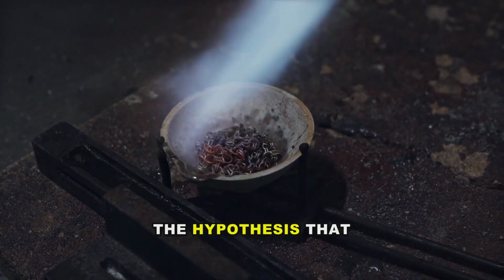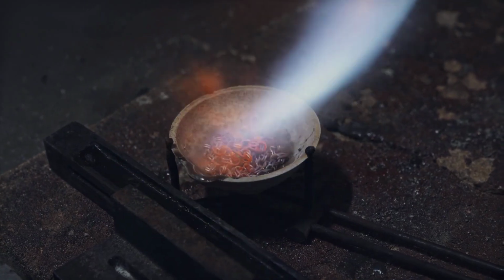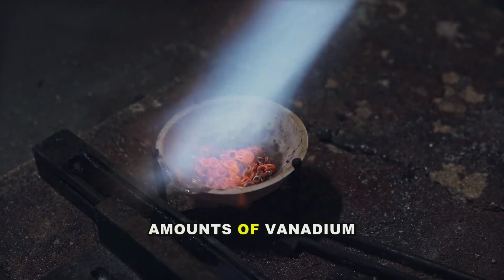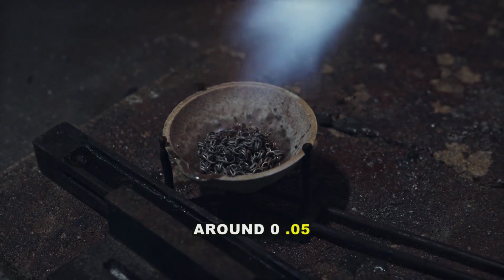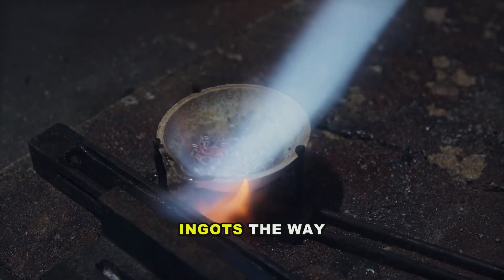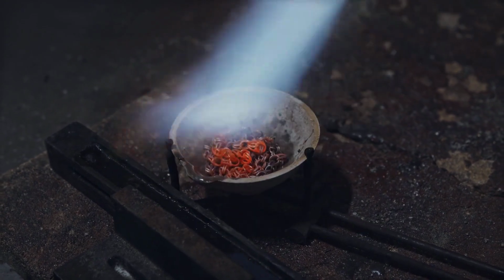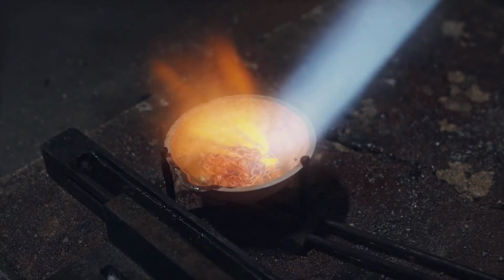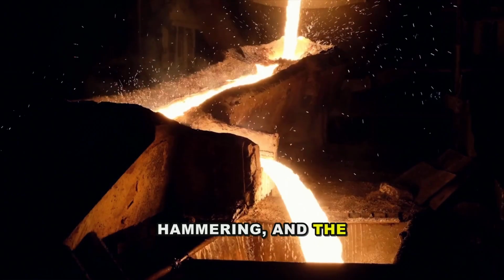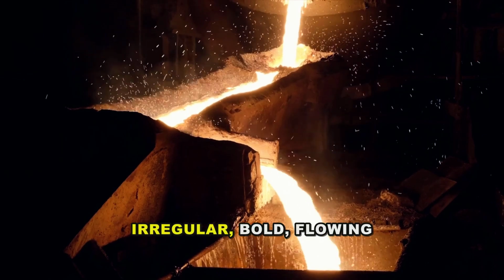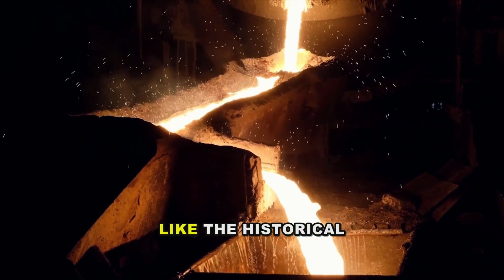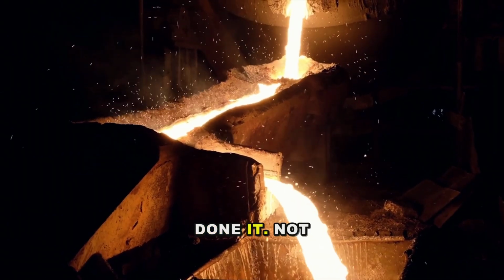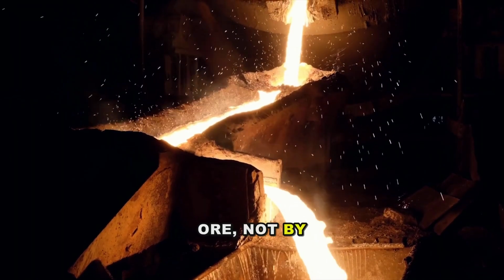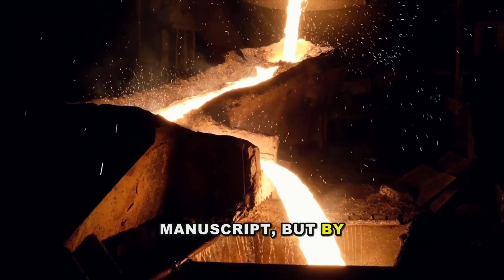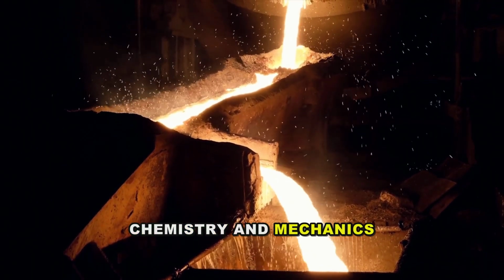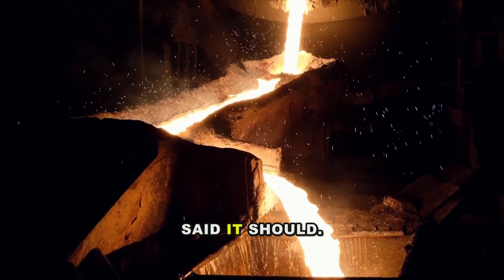They started with the hypothesis that trace elements were key. Pendray began adding carefully measured amounts of vanadium to his steel, around 0.05% by weight, and forging the ingots the way descriptions of Wootz production suggested. Low heat, slow cooling, hours of patient hammering. And the patterns came back, not faint, not irregular, bold, flowing bands that looked like the historical examples. They had done it, not by finding ancient ore, not by rediscovering a lost manuscript, but by reverse engineering the chemistry and mechanics until the steel behaved the way the old smiths said it should.